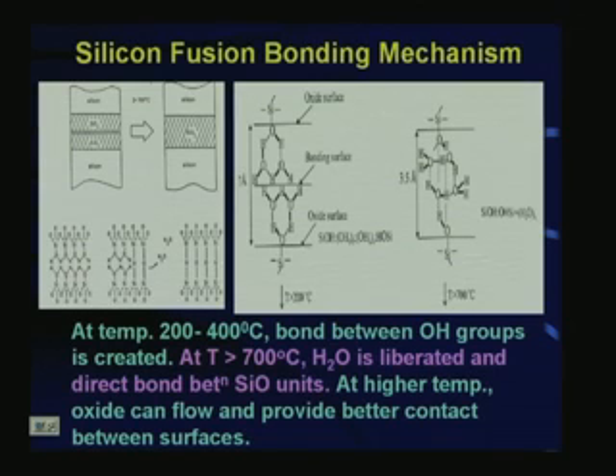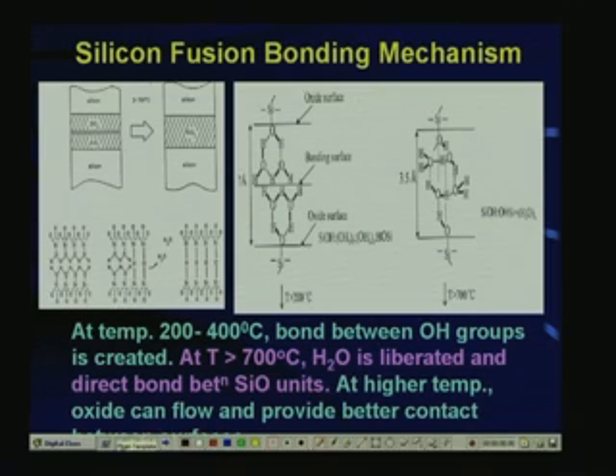Now, the bonding mechanism is further shown in this diagram, and here you can see there are 2 or 3 kinds of reaction steps taking place. One is in the range of 200 to 400 degrees C. Now, the diagram shown here is for when temperature is greater than 200 degrees C. This is the oxide surface, and here is the silicon, and you see this is the bonding surface. Here is silicon and here is silicon. Now, the gap between them is 7 angstrom, only a very small gap, and that is the native oxide, and that oxide which is there on the silicon surface absorbs the H2O molecule, and after absorption of the H2O molecule, the H2O is decomposing the oxygen hydrogen bonds.